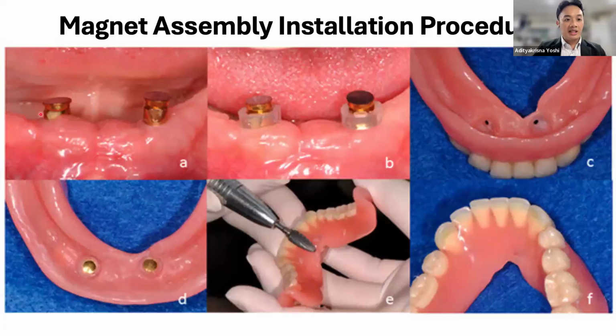So this upper part is called the magnet assembly. And after that, a silicone holding to prevent the attachment of the self-curing resin to the lower part that can flow into the undercut parts is placed in this position. And then on the denture intaglio surface, a spillway or vent hole was prepared using a burr. And into this space, a self-cure acrylic resin was applied. And then after positioning the denture onto these implants, the pickup procedure was performed.